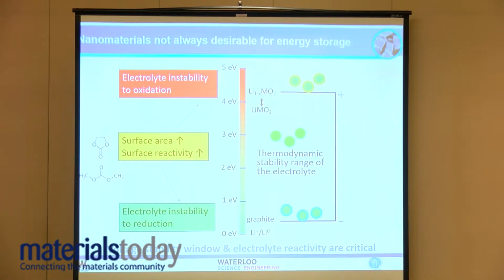Here I have plotted the potential of lithium down at the bottom, so it's -3 versus the standard hydrogen couple, but I put it at 0 just to reference everything to it. And here is the redox couple about 4 volts above that of lithium for a typical layered metal oxide, which is what is used in our cars and most devices today.